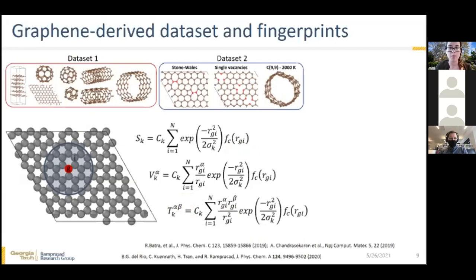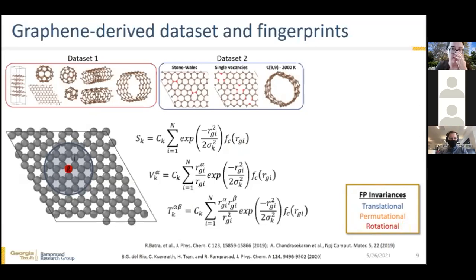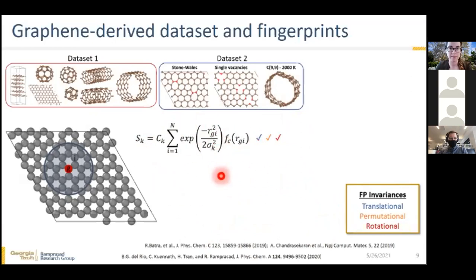Now, one important thing when creating fingerprints is that they need to comply with the invariances of the target property. In our case, the density of states is translational, permutational, and rotational invariant. The translation invariance is introduced by using the distance between the atoms and not the position. And the permutation invariance is introduced by summing over all neighbors. Now, regarding the rotational invariance, even though the scalar fingerprint complies with it, the vector and tensor fingerprints do not. However, we can develop other expressions which are rotationally invariant, as we can see here.